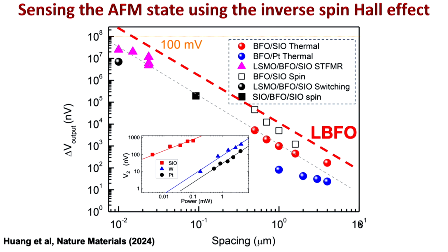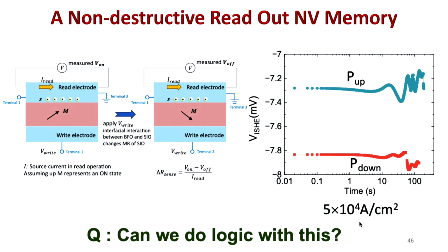get to numbers like this, which then comes to devices which are shown schematically here, where you can have a very simple capacitor-like structure. I can manipulate the magnetism. I can read out the changes in the magnetism with the inverse spin Hall voltage. That spin Hall voltage is now approaching a millivolt, not 100 nanovolts, but 1 millivolt. And we think with some tuning, this is a 100 nanometer thick sample. Going down to 10 nanometers, doing very careful measurements, we should be able to get more of those. Now, the big question that we don't know the answer to is, can you do logic with this? We think we can do memory with this, but logic is a lot more difficult.